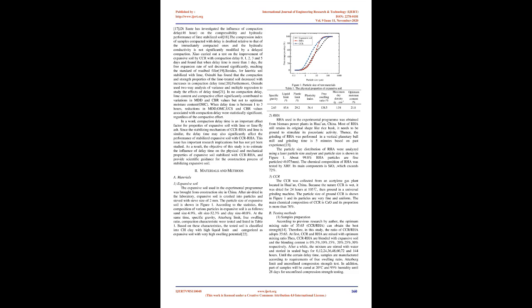2. Materials and methods. A. Materials. 1. Expansive soil. The expansive soil used in the experimental program was brought from a construction site in China. After being air-dried in the laboratory, expansive soil was crushed into particles and sieved with a sieve size of 2 mm. The particle size of expansive soil is shown in Figure 1. According to the statistics, the composition of various particles in expansive soil is as follows: sand size 6.9%, silt size 52.3% and clay size 40.8%.